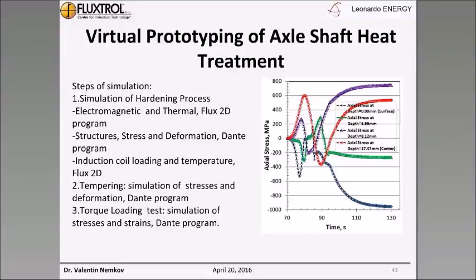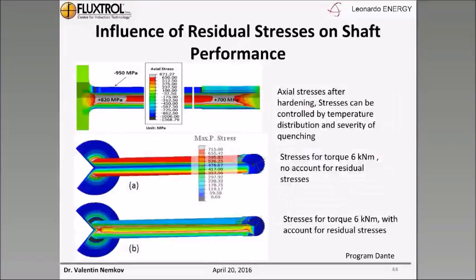At the same time, we simulate structural transformation, stress and deformation using the Dante program. After that, we simulate tempering, simulation of stresses and deformation with the Dante program. It could be induction tempering or furnace tempering. And finally, torque loading test, simulation of stresses and strains using the Dante program. The results are here.